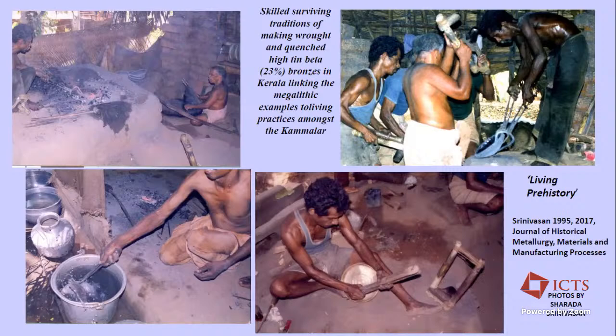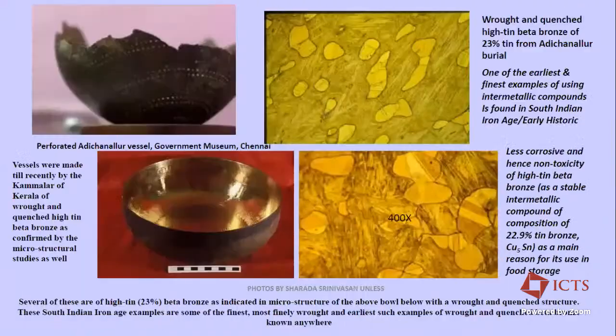And then finally, that step of quenching is very important, that again, heating it to high temperatures so the beta phase forms and then quenching, because only then you retain that martensitic beta phase. And one reason why that alloy was also preferred is because when it's polished, it also looks very bright and golden, just like gold. So in a way, there are these strands of what we might describe as living prehistory, as D.D. Kosambi also comments on.